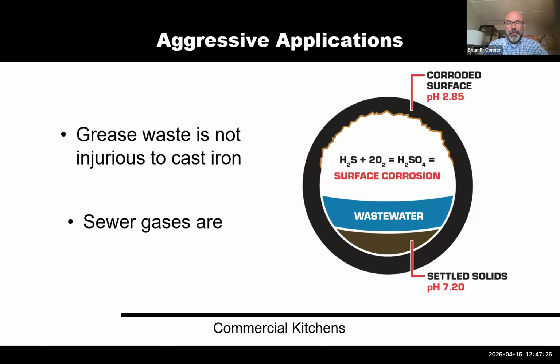And in some cases, there is corrosion caused by the solids from waste being left behind. I tell you, if you can point me to a commercial kitchen that is cleaning their waste traps out, as they're supposed to, it'll be the first one I've ever seen. These grease wastes create an environment where solids are left behind. It creates microbes, and the off-gassing of this can be very corrosive. So commercial kitchens are one where these enhanced coated cast iron products have been specified and used with great success, because they have the ability to handle pH ranges many orders of magnitude beyond that of standard iron.